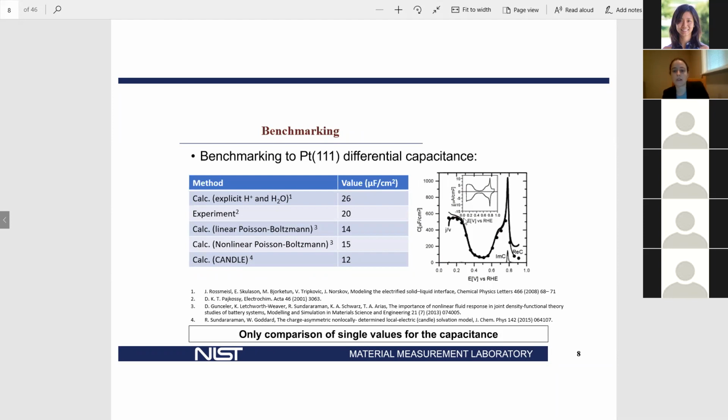This is also the pseudocapacitance associated with the hydrogen evolution reaction happening on the platinum electrode. So we don't actually know what the true capacitance of the platinum, or even the platinum with the hydrogen, is at these potentials. Then we move to a lower region, which has been characterized as the double layer region, but it still has fairly high values.